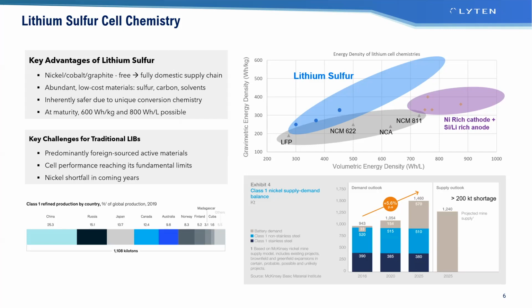The other thing is that sulfur itself is an insulator. So if you tried to put a block of sulfur down, you wouldn't get much of a battery, because it doesn't really want to move electrons. So you have to have some kind of matrix that is conductive, right? So what does our graphene do? Our graphene provides the conductive matrix, and it controls the polysulfide shuttle. Okay, it's still difficult. It's not perfect.